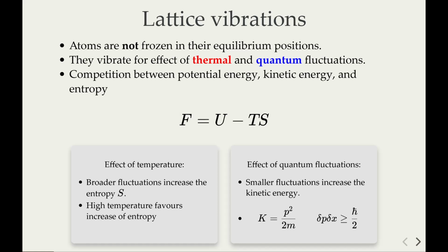But even if the temperature is zero, so we are at 0 Kelvin, we still have vibration, and this is a result of the Heisenberg uncertainty principle. You can clearly see that if we localize the ions too much around the minimum of their position, we have an uncertainty on the velocity of the ions, on the momentum.